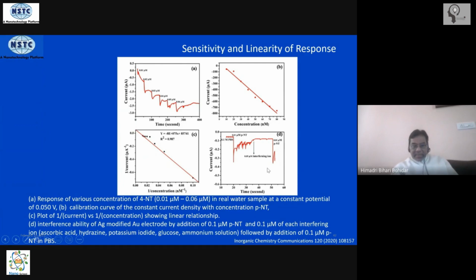Now, this analyte, in the presence of other interfering compounds like ascorbic acid, hydrazine, potassium iodide, glucose, ammonia solution. This is the signal for our sample, our analyte. Okay, this is p-nitrotoluene here. And for the other interfering cations, you see there is nothing. The signal is not there. The dominant is this and this only. Others are hardly contributing to it. They're seen as the background, basically noise. So it's not sensitive to detection of potassium iodide, glucose, or ammonia, or ascorbic acid, or hydrazine. So this also implies the specificity of this technique for the detection of nitrotoluene.